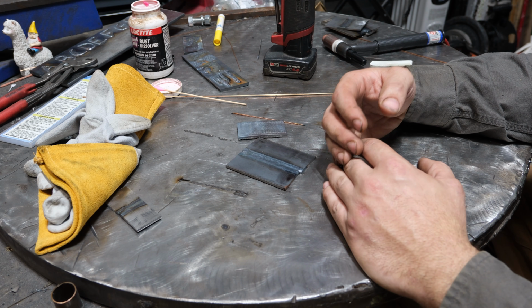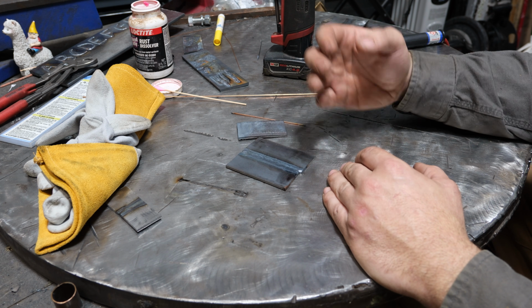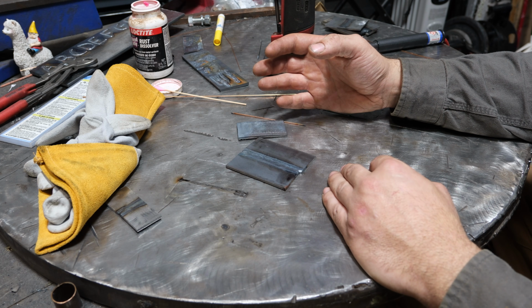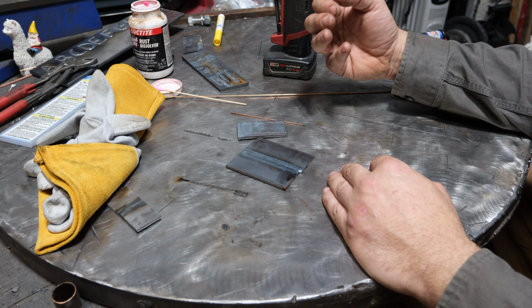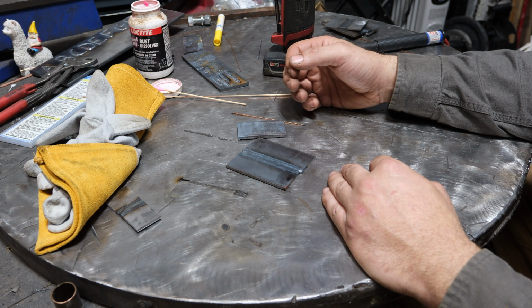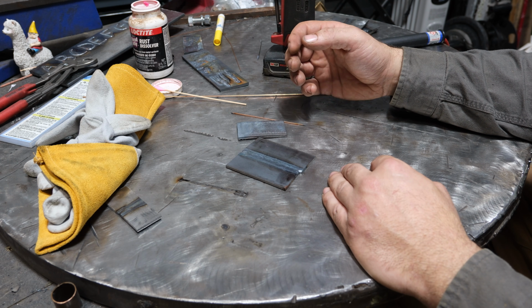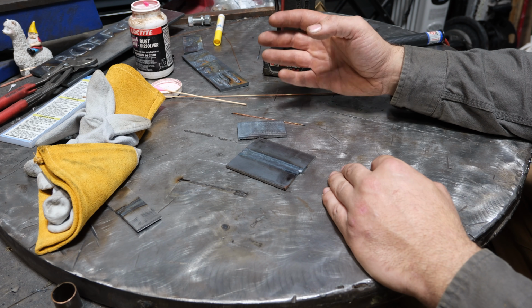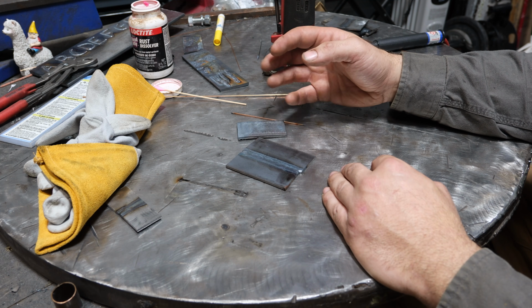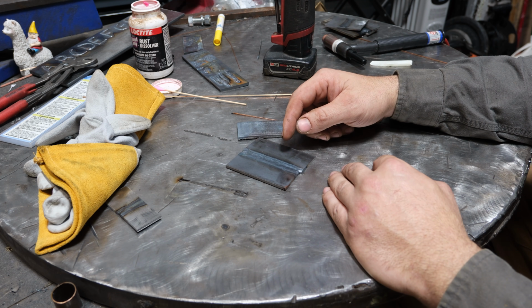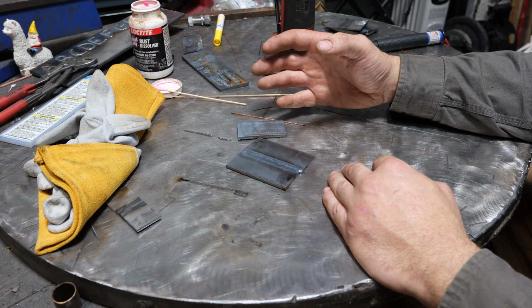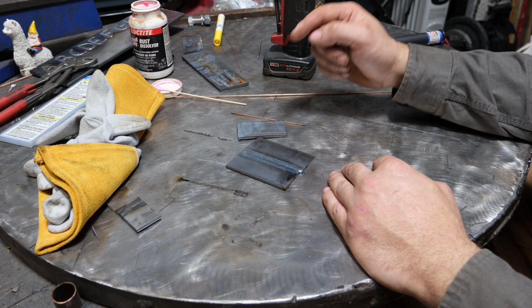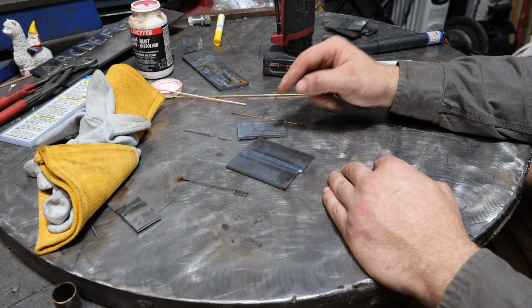So again, I hate to say it, to beat a dead horse, I can't stress enough how important it is that you do welds and then you cut them, you etch them, you break them, you look at it, because what you're seeing on the surface might not coincide with what's actually going on internally. And you do not know what's going on internally on your welds unless you test what you're doing.